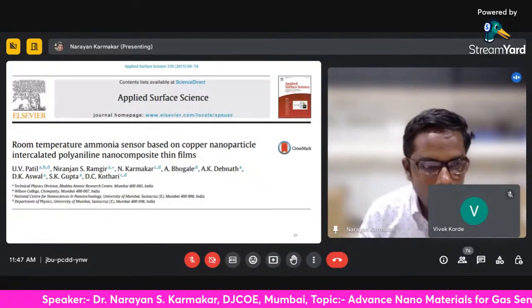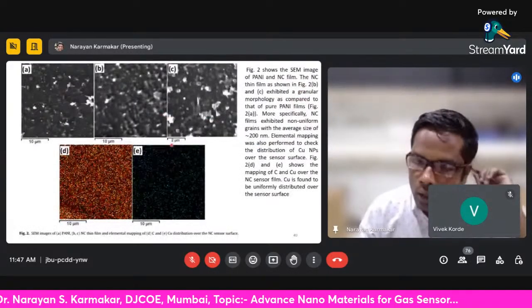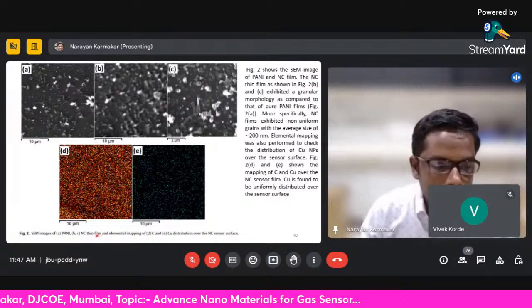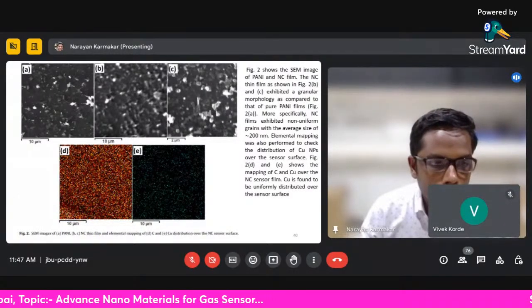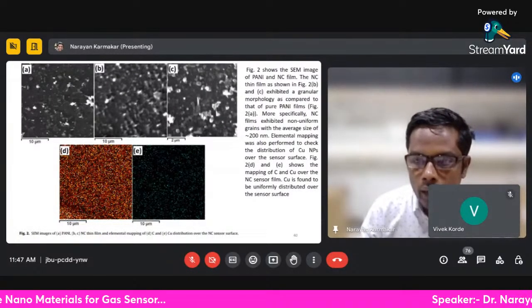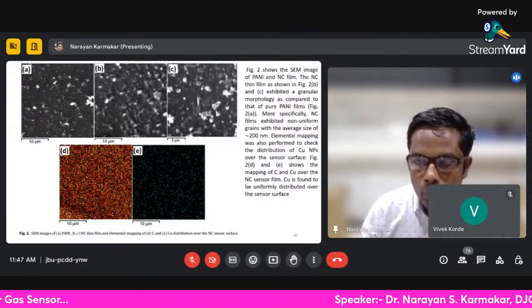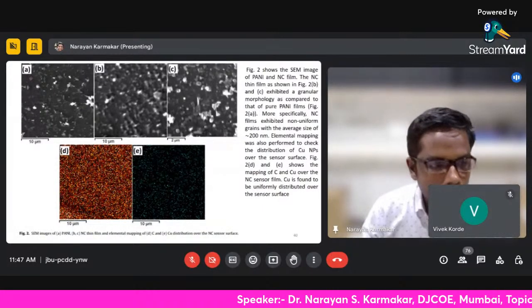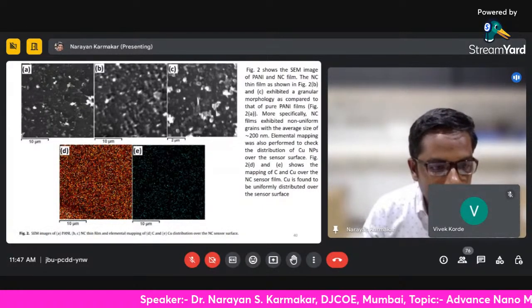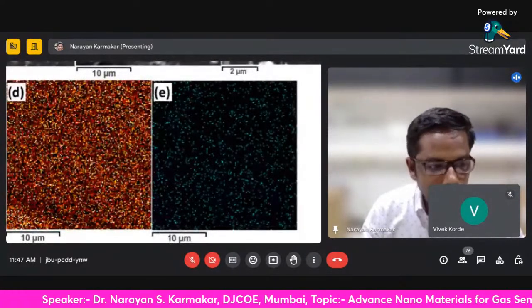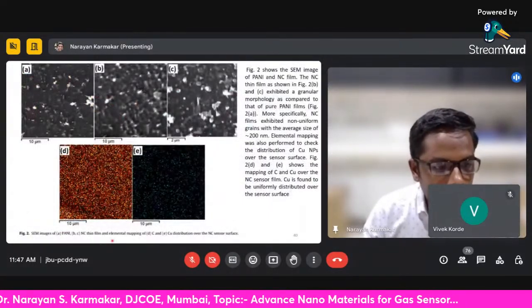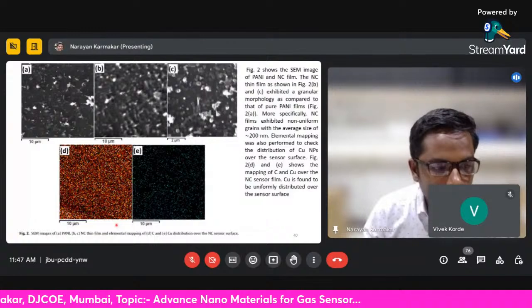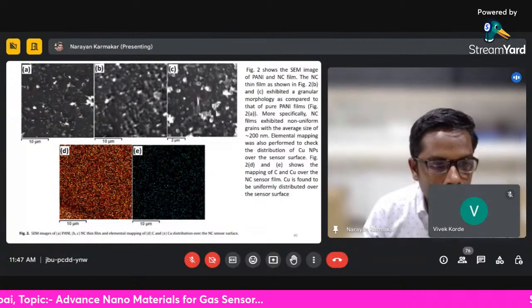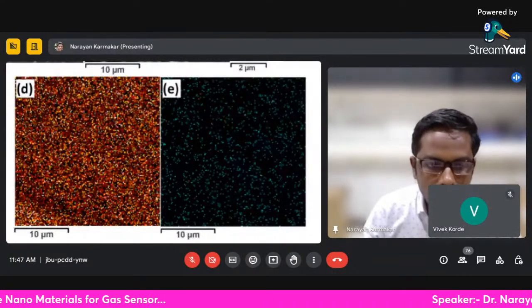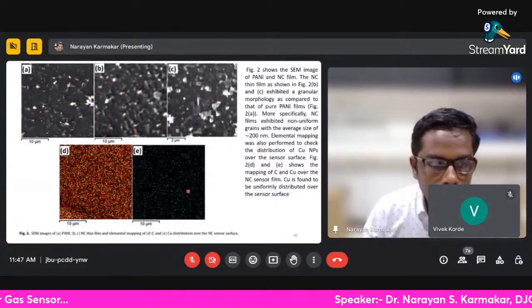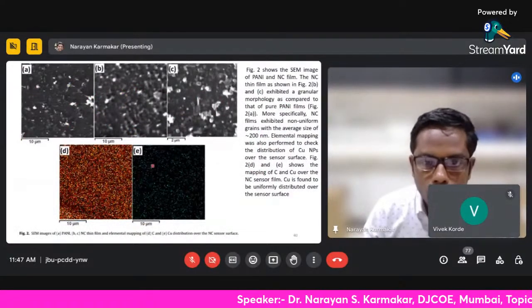So when you make a nanocomposite, we always check whether the nanocomposite is properly made or not. What you do is this - we have synthesized the copper nanocomposite and done the mapping of this sample. When we did the elemental mapping of the copper, we can see a uniform distribution of copper using this nanocomposite. So we can see there is a good formation of the nanoparticle.